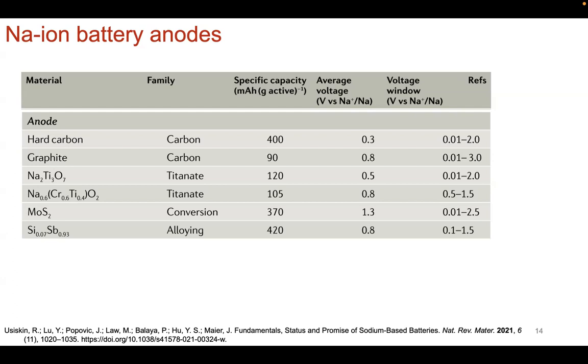Obviously, hard carbon is a historical term for disordered carbon. Now, the lithium titanate, the titanate base family, you also see that here for sodium titanate base sodium ion battery anodes. There's also a number of conversion and alloying materials that you see for the anode that you've already seen for lithium ion batteries as well. So we'll focus on the hard carbon because a lot of work has been done there to try to understand how do we store sodium ions in these types of carbon materials, and then also how do we then change the microstructure and design these anodes so that they can store more sodium ions. Okay.